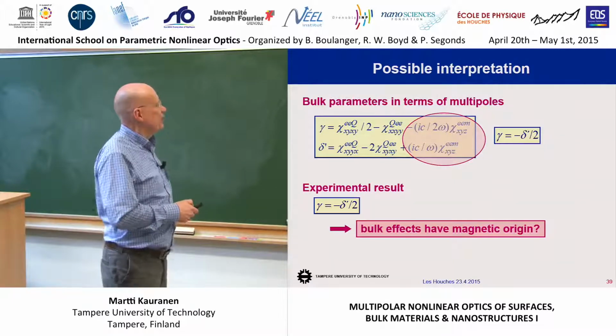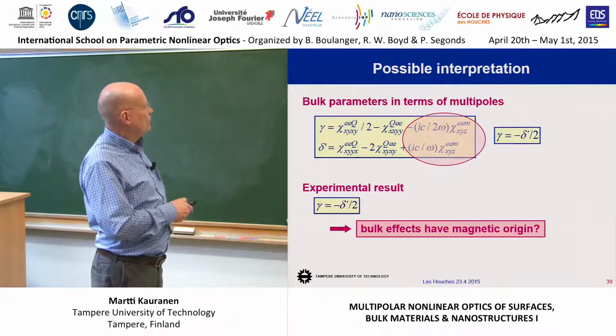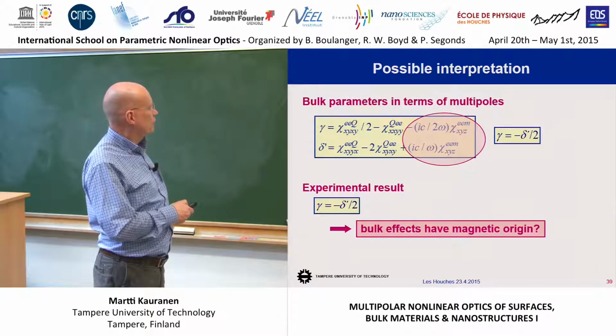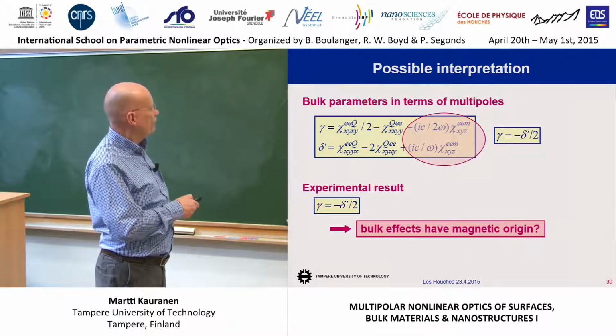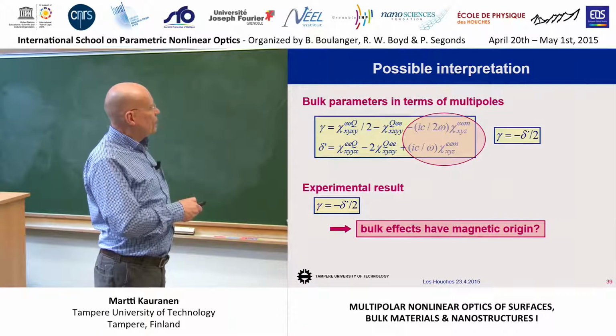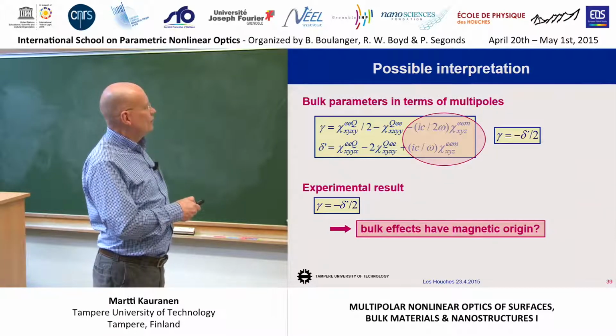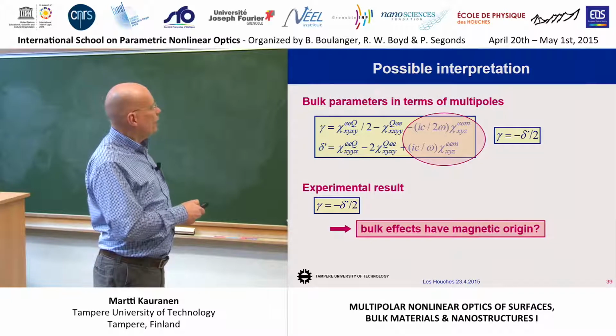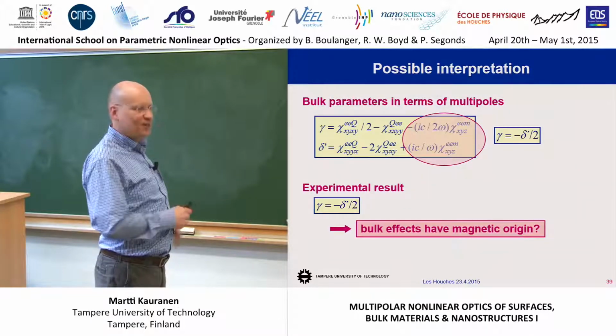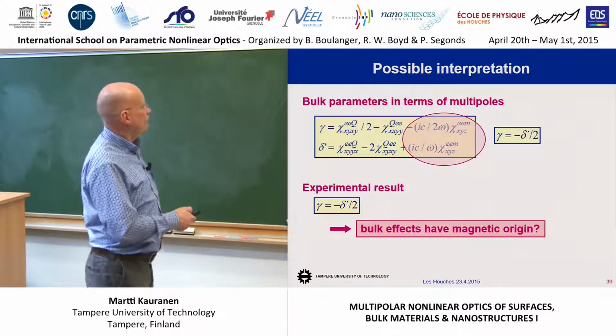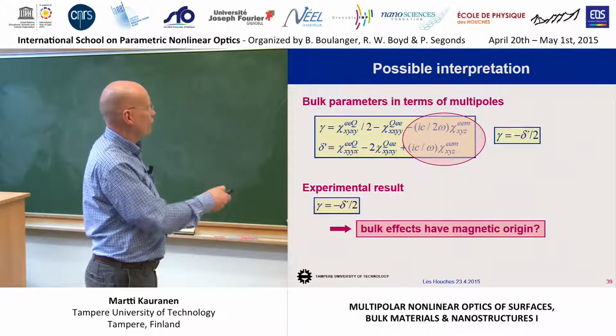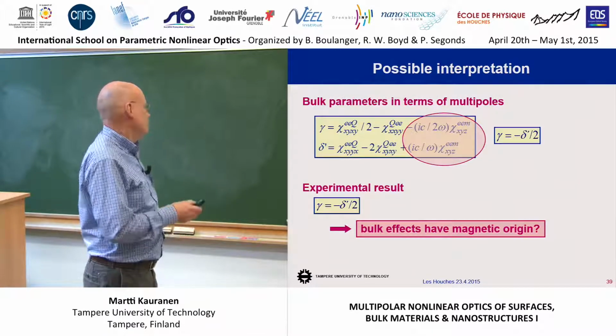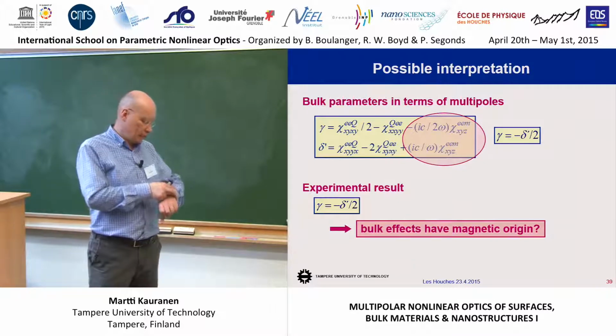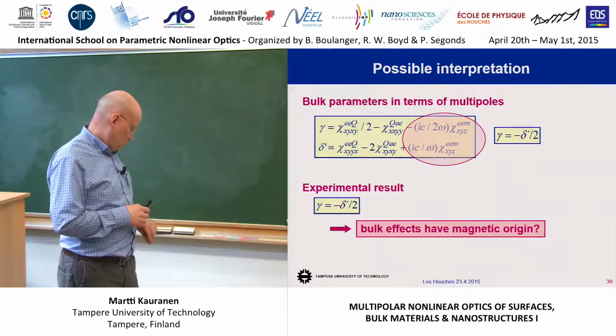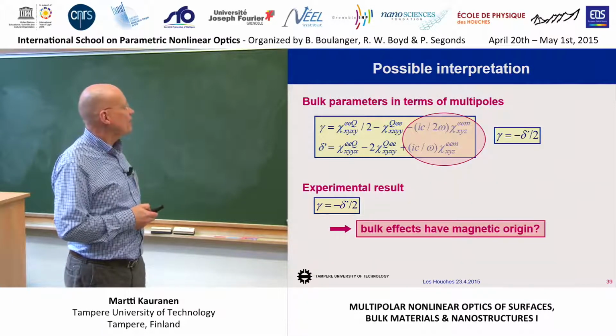The problem that we have now is that if you look at the quadrupole part, if the response was dominated by the EEQ tensor, then gamma would have to be 1 plus 1/2 of delta prime from here. But then the problem is that for the QEE tensor, the components that appear are x, x, y, y, and x, y, x, y. And there's no fundamental symmetry rule that would connect these components to each other. So there's still some remaining uncertainty. But again, if these were assumed to be equal, then the quadrupole part would have a plus sign here. So all this hand waving really suggests that magnetic effects do play an important role here. Okay, then